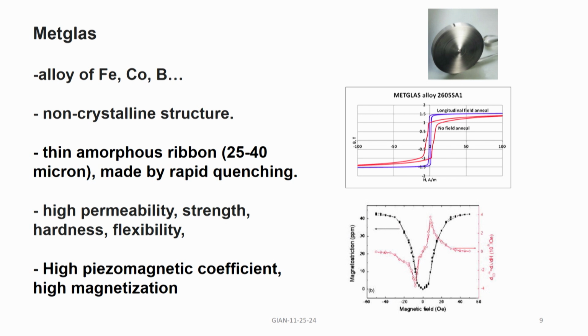It is used in transformer cores because of the high permeability, and we have used it in many of the composites. And also the German group, as I mentioned earlier, they made very good magnetic sensors by combining the Metglass with aluminum nitride to make these magnetic field sensors for magnetocardiography. Okay. So, it has very high magnetization, about 1.5 Tesla, that is pretty high, and also the magnetostriction is shown here.